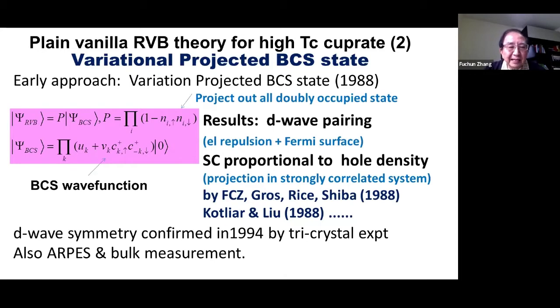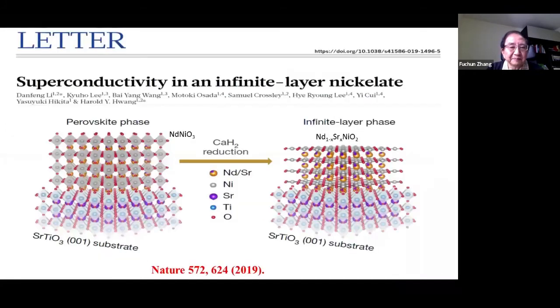The exact calculation is variational Monte Carlo, but analytically we can do some approximation. And the detailed study of this trial wave function leads to a d-wave symmetry of the pairing, which was confirmed in 1994 by tri-crystal experiment, and is also consistent with ARPES and many other bulk measurements. So with that, I'd like to go to the discussion of the nickelate. Maybe I'll just stop quickly to see if there are any questions.